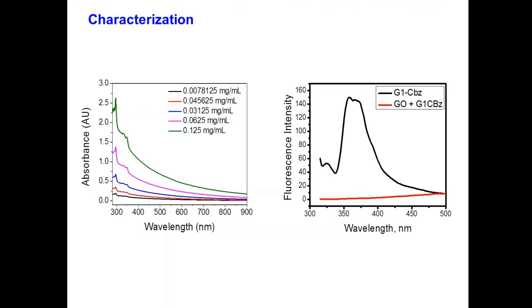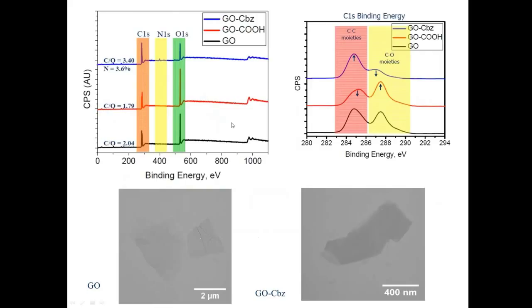This is the spectra of the modified graphene oxide, as well as the fluorescence, indicating the fluorescence of the Carbazole units. By XPS, we can confirm that the graphene oxide was modified by the Carbazole groups.